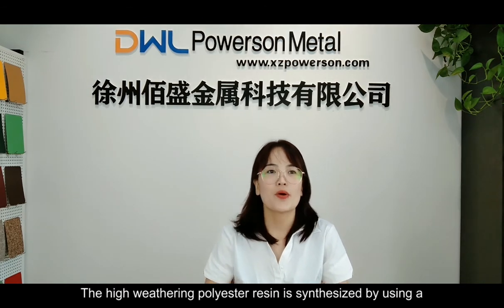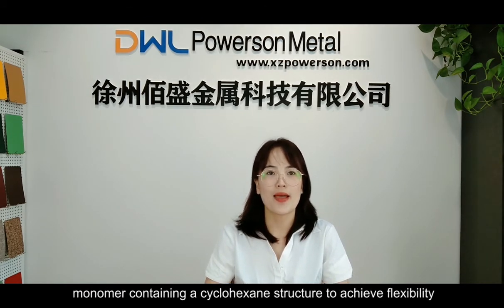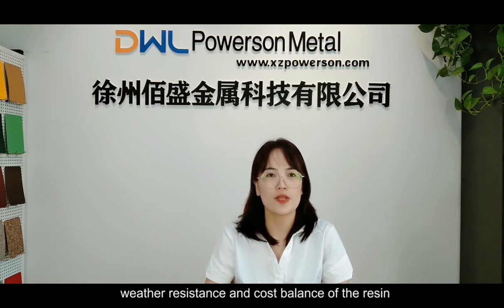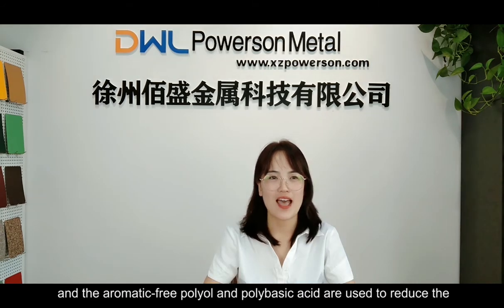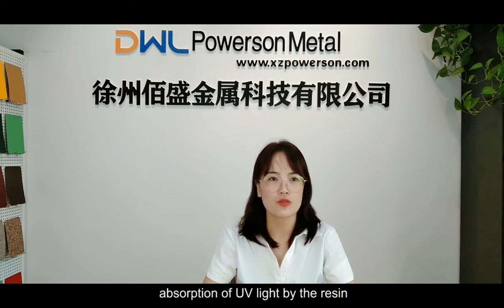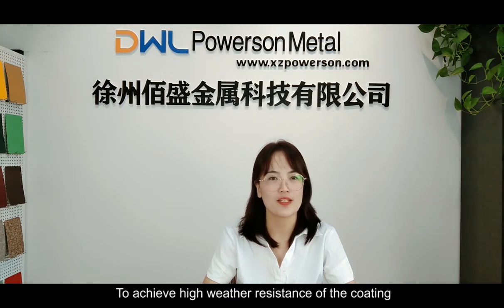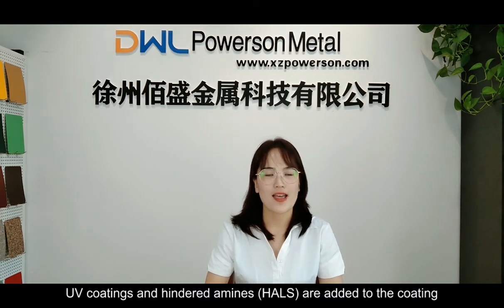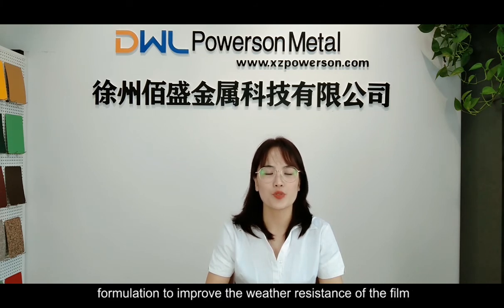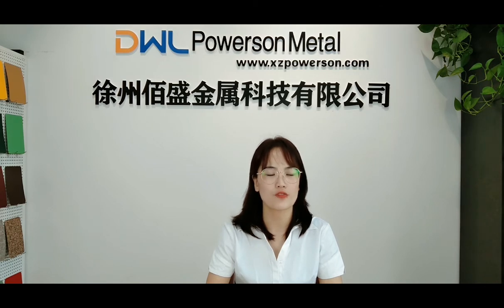The high weathering polyester resin is synthesized using a monomer containing a cyclohexane structure to achieve a balance of flexibility, weather resistance, and cost of the resin. And aromatic-free polyol and polybasic acid are used to reduce the absorption of UV light by the resin to achieve high weather resistance of the coating. UV absorbers and hindered amines are added to the coating formulation to improve the weather resistance of the film.